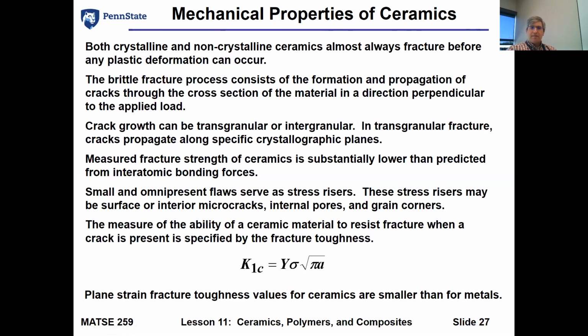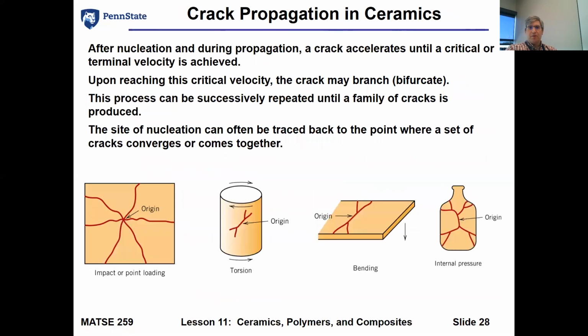The fracture strength, as we said, is very low. And so when we start thinking about that, we have these stress risers all throughout. We have these flaws, these defects, these pores. They're rife throughout the ceramic material. So the material is full of stress risers. And so when we start thinking of the ability to resist fracture, we go back to our K1C values, the plane strain fracture toughness. Now, as you can imagine, since the cracks propagate very rapidly, these toughness values are much lower. And so we start to see these different things.